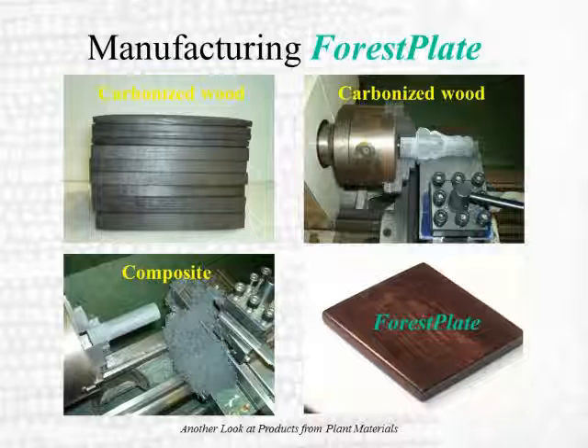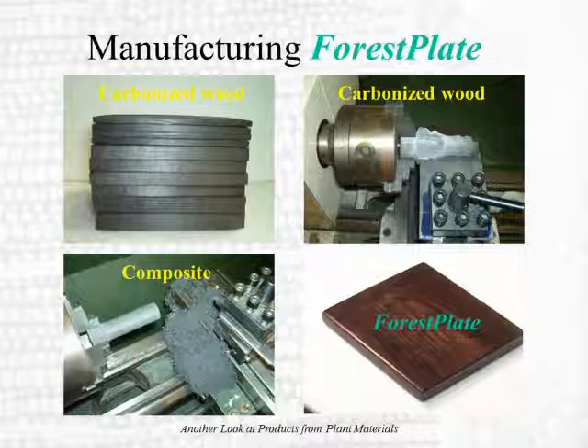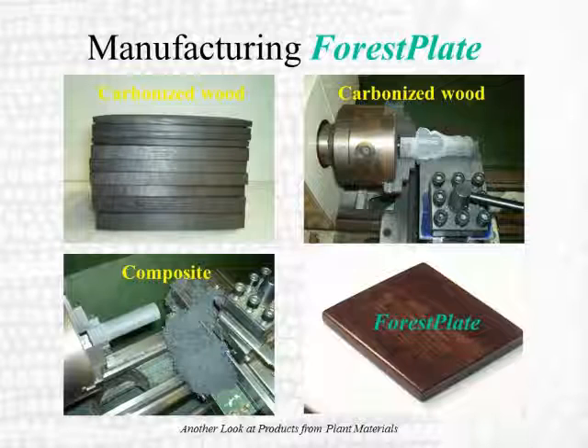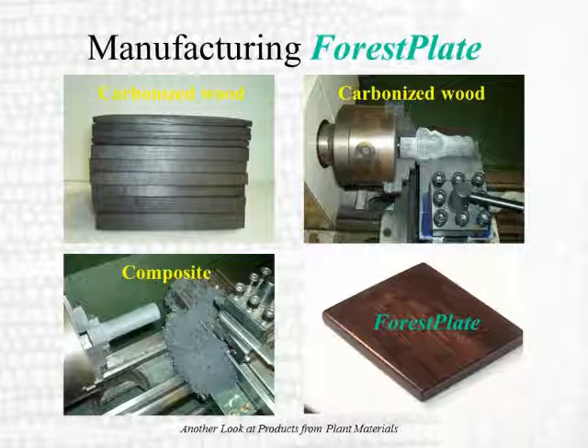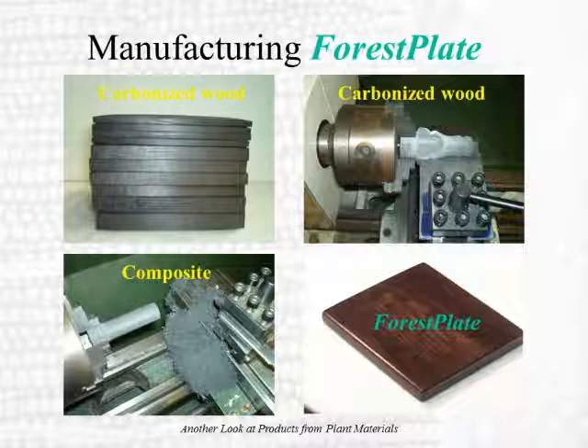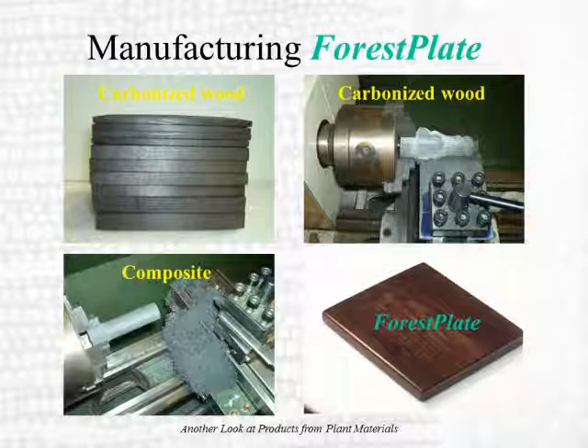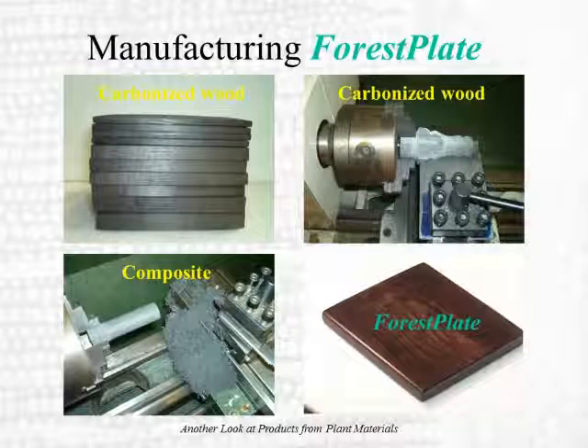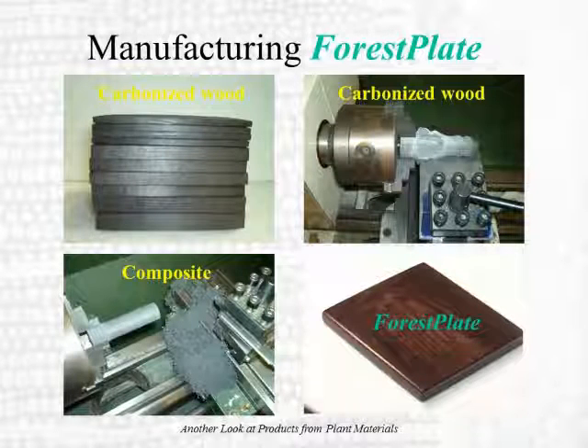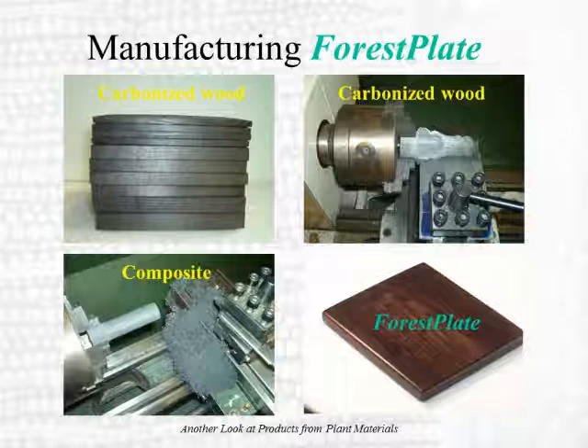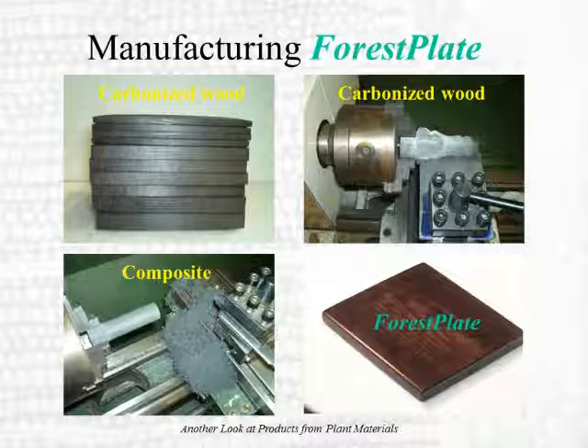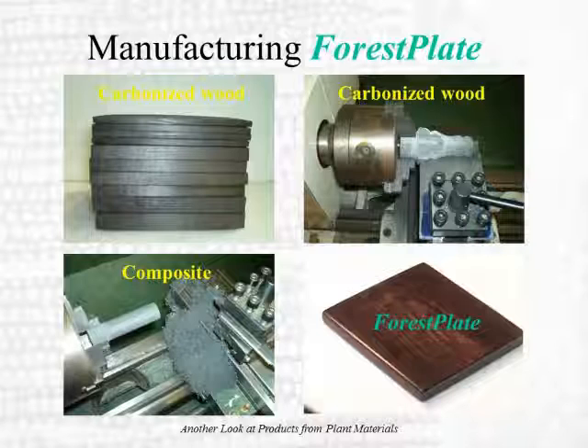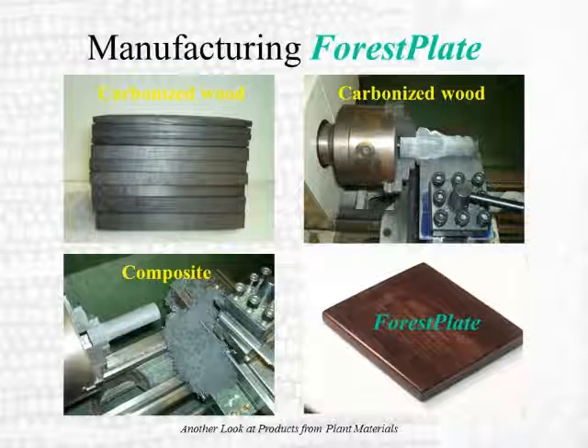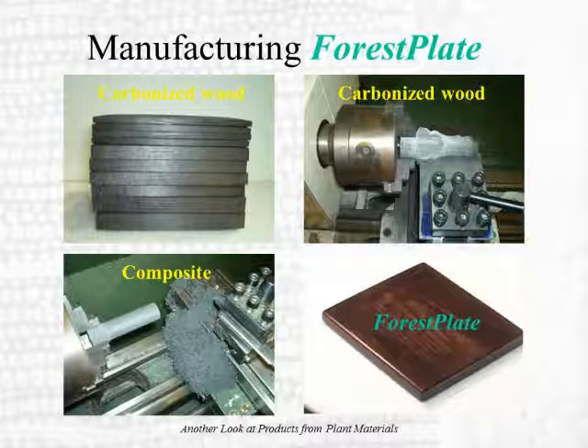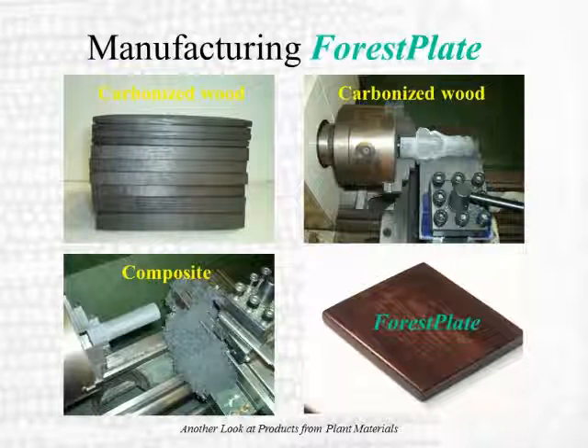One of the main steps in doing this right, whether you're making the ForestPlate or you're making ceramics using this process, is the carbonized wood has to be made in such a manner that you don't get cracks and that you can efficiently use the whole volume of the charcoal, which means essentially don't let it warp, split, crack, and so forth. So we've been able to accomplish that and get, here's boards that were 6 inches by 6 inches in dimension. That size, because that's the limit of what our furnace would allow us to make.